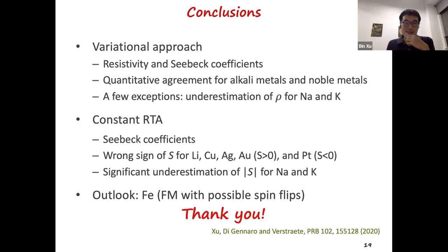To summarize, we use both variational approach and constant RTA to predict the transport properties of alkali metals and noble metals. For variational approach, we can predict both the resistivity and Seebeck coefficients. And the agreement is quantitative with the experiment except a few exceptions. But for constant RTA, it cannot fully predict the Seebeck coefficient. And it predicts the wrong sign of Seebeck for lithium, copper, silver, gold, and platinum. And for sodium and potassium, it predicts the correct sign, but the magnitude has some significant underestimation.